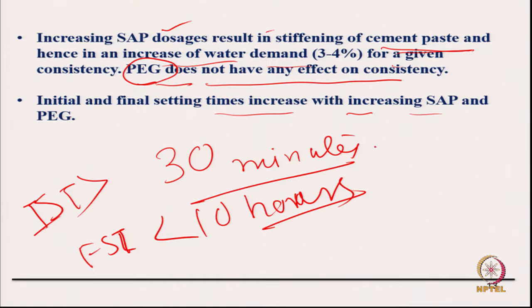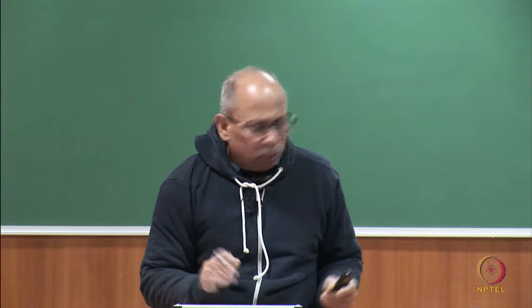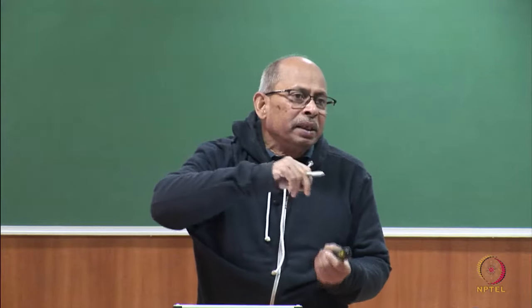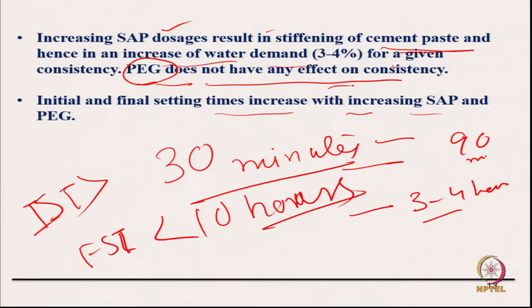Most of the cements, what you will find is, the initial setting time is much higher, going even to 90 minutes, 1 hour or so, and the final setting time should be about 3 to 4 hours, not even 10 hours. Now, these are measured by some empirical test called the Vicat test, actually the Vicat apparatus. I will not go into that, or the penetration resistance test, etc. Now, what does this do? This increases the initial setting time. So, if it was about 45-50 minutes, now it will go to 90 minutes, I have no problem. It increases the final setting time. As long as that final setting time is not more than 10 hours, I have no problem. Many of the cements will have 3 to 4 hours. So, let it increase a little bit, but you have to check that it does not increase beyond 10 hours, then you will have issues of demolding.